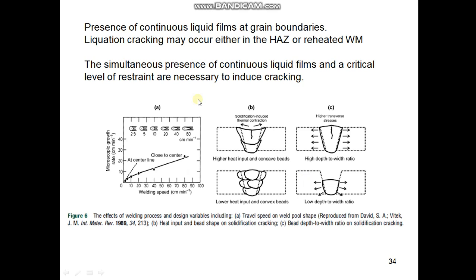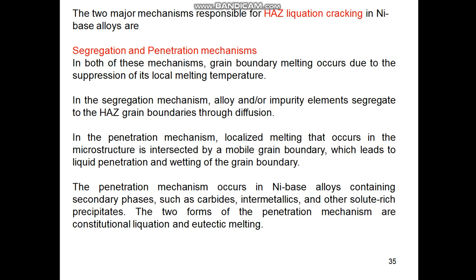There are two major mechanisms responsible for the HAZ liquation cracking in nickel based alloy. One is the segregation and penetration mechanism. In this, due to the segregation of the impurity elements at the HAZ grain boundary through diffusion, localized melting will occur, and the microstructure is intersected by a mobile grain boundary. This leads to liquid penetration. So your liquid will fill the cracks, and you have a low strength at the crack region, and the grains will be stronger than the grain boundaries, and under the contraction stresses there will be separation of the grains at the grain boundaries. It is because of the wetting of the grain boundary.